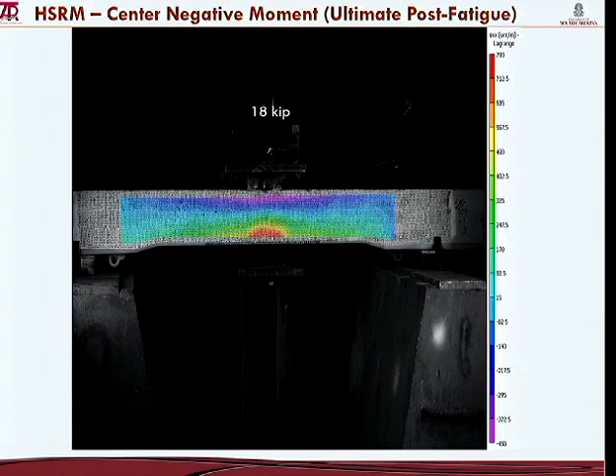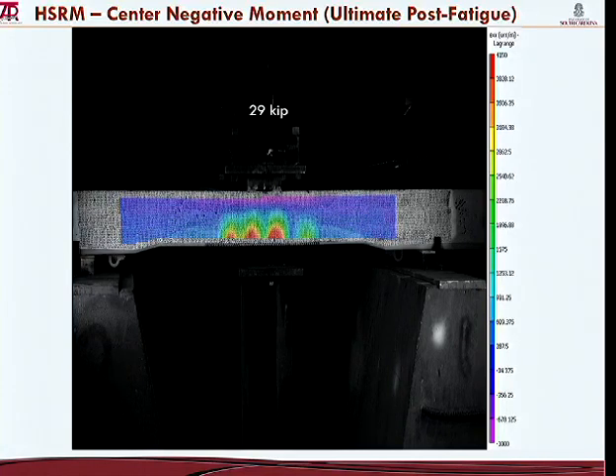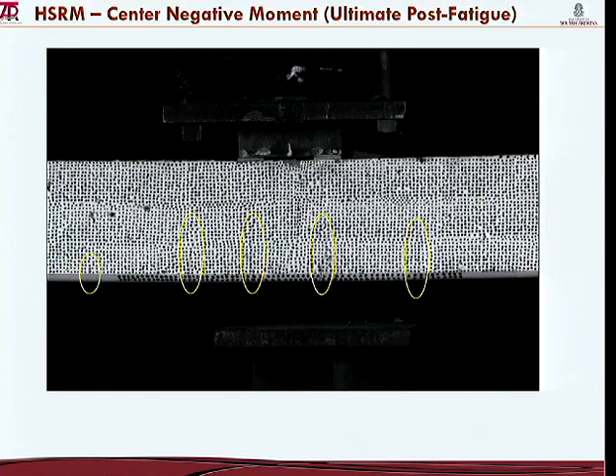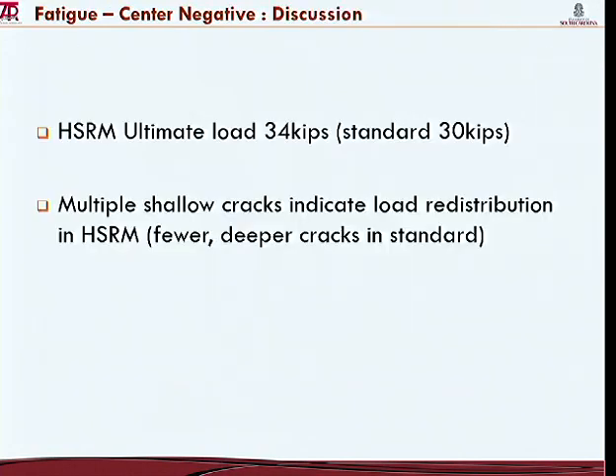Now we start seeing increasing strains at 20 kip, 10,000, and now 2 cracks at 22.5. And now 2 more cracks as the load increases. And yet another crack. So by the time it failed, it had developed 5 different cracks that had not propagated all the way to the top. So ultimate load, 34 kips. The standard, it was about 30 kips. Multiple shallow cracks indicate higher redistribution, and we had fewer but deeper cracks in the standard tie.